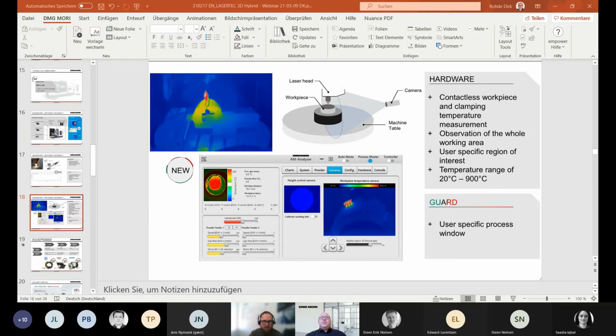For all repairs, we see that the repair area is so small that it doesn't have a full impact on the part. When you have a full print, you would take it off, stress relieve it, and then machine it, definitely, to avoid any trouble which is coming later from bending or deforming the part due to the heat impact. But that's typical in every welding process and also with every other additive manufacturing process like SLM or DED, doesn't matter. It's all the same, but a good question because you have to think about it.